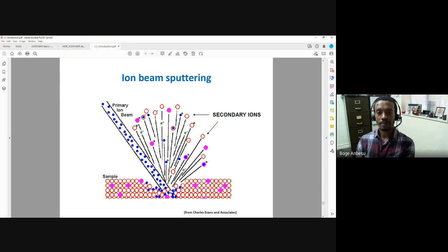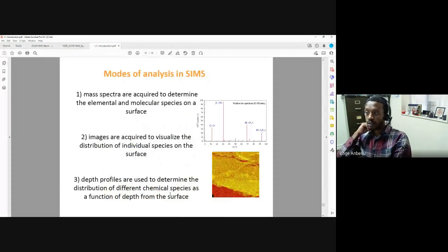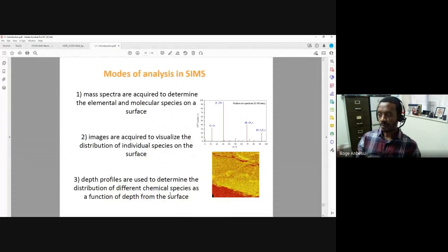You also know, based on the abundance of these fragments coming from the sample, if lots of fragments of gold are coming, it must be because the sample is high in concentration of gold. If there are sulfur fragments coming very repeatedly, maybe it's a sulfide sample you're looking at. So you can identify what material you have in there, what composition. You also know how much of that particular composition is coming. So the point here is, from the mass fragments, we can detect those fragments and measure the mass, which tells us the identity of what is in the sample.